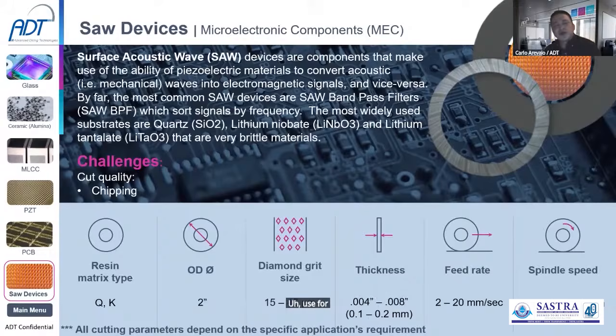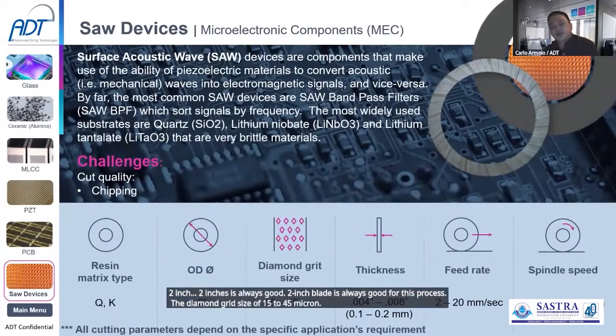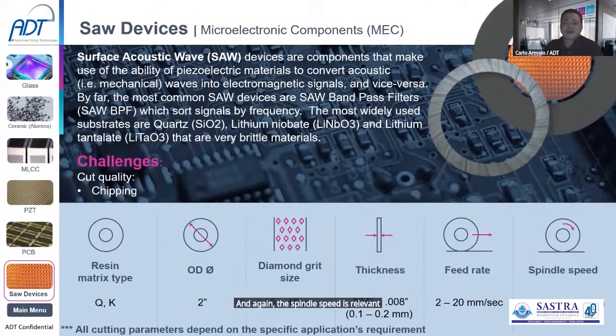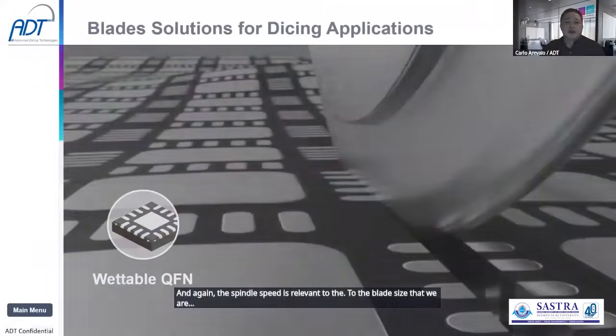So we have a few models that we use for this particular application, mostly on 2-inch diameters, because if you're dealing with a very hard or very sensitive type of material, for sure the exposure setup has to be at a minimum, or a very balanced blade. So 2-inch is always good for this process. With a diamond grit size of 15 to 45 micron, thickness range of 100 to 200 micron, and the feed rate is on the low side. It can be as slow as 2, but the best thing that we can do is 20 millimeters per second. And again, the spindle speed is relevant to the blade size that we are going to use.